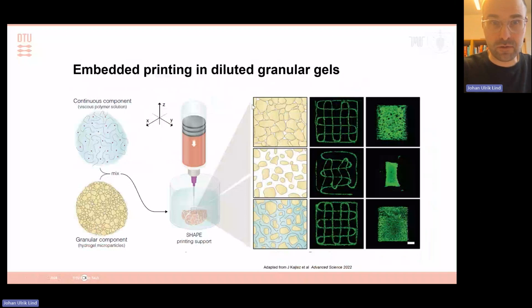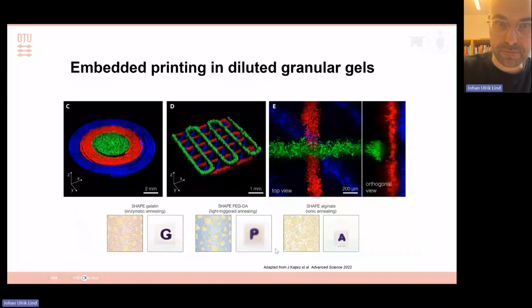If you print into a nicely jammed microgel, you can print nice features with a high spatial resolution. If you then start to dilute it, like you add a little bit too much media around the microgels, then you lose this spatial resolution. What we found is that if the continuous component in between the microgels is of a high enough viscosity, you can still have a higher spatial resolution, but now you have more space for the cells to grow into, and you have better control of what this environment the cells are growing in looks like.